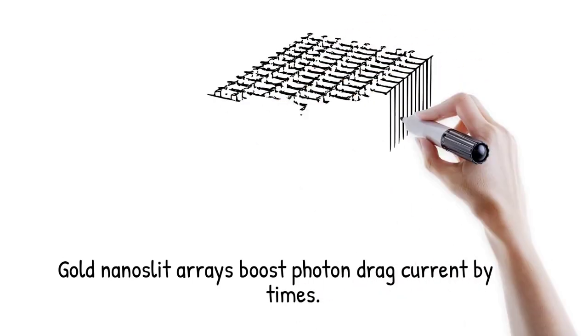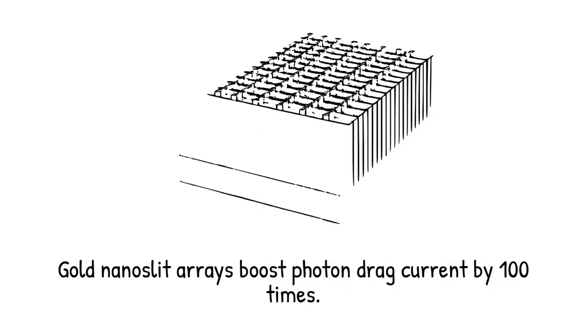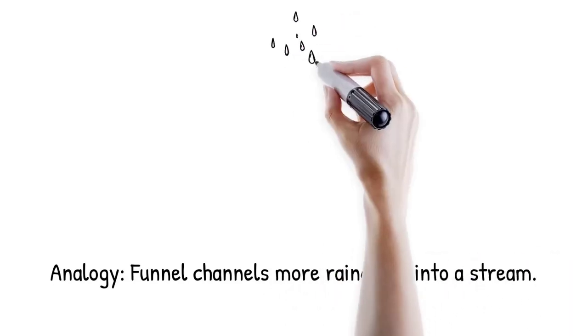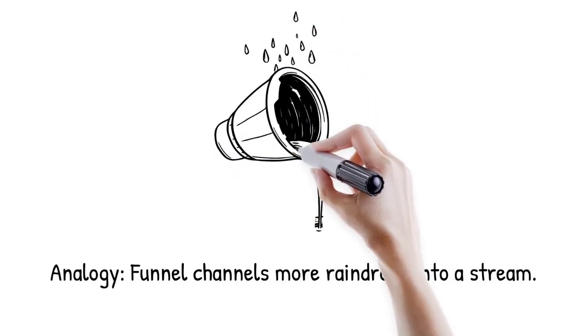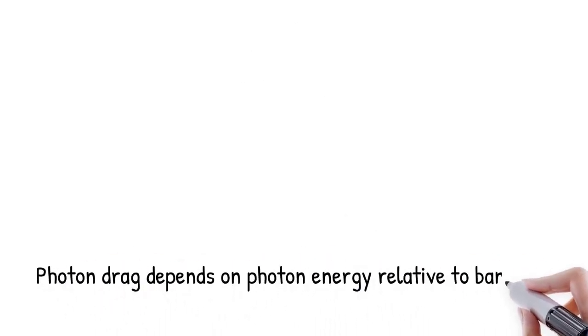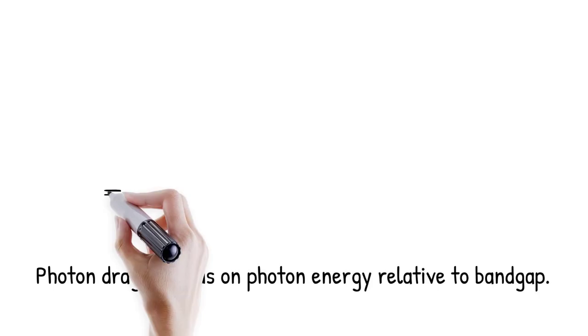A gold film with nanoslit arrays exhibits a 100-fold increase in photon drag current at the plasmon resonance wavelength of 800 nm. It's like adding a funnel to catch raindrops. You suddenly channel much more water into a narrow stream. Photon drag depends on the photon energy relative to the electronic band gap and dispersion of